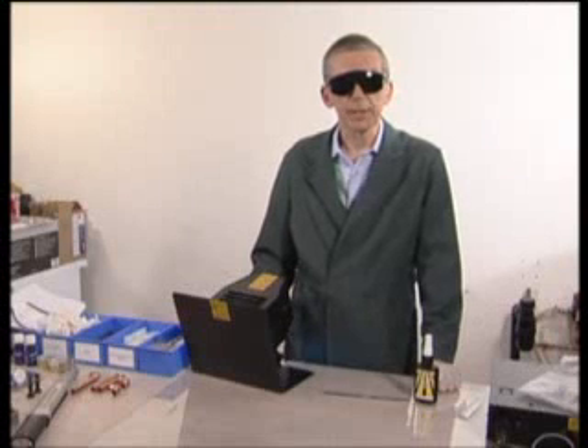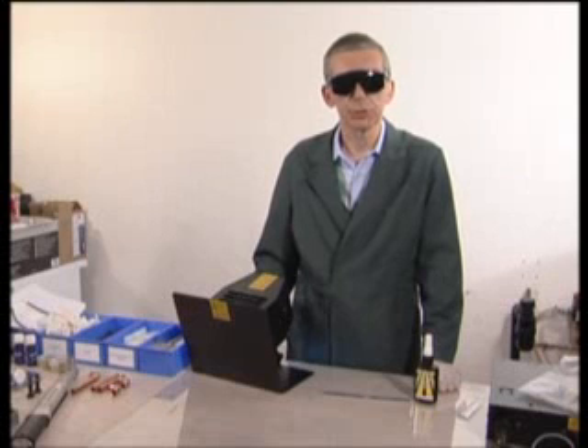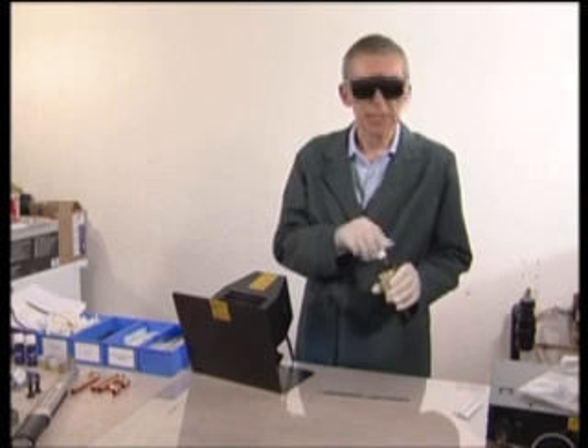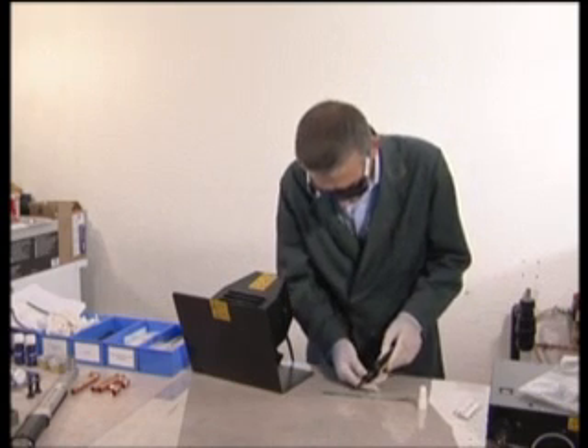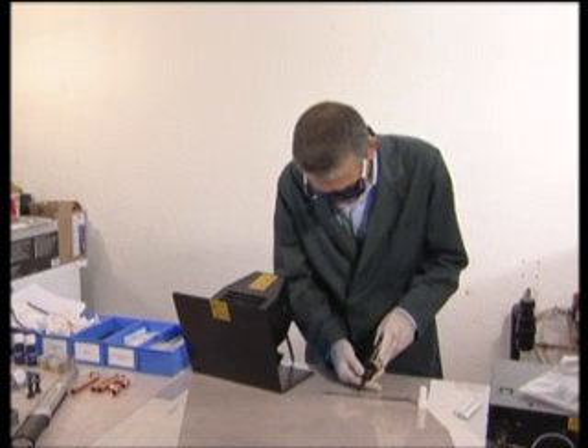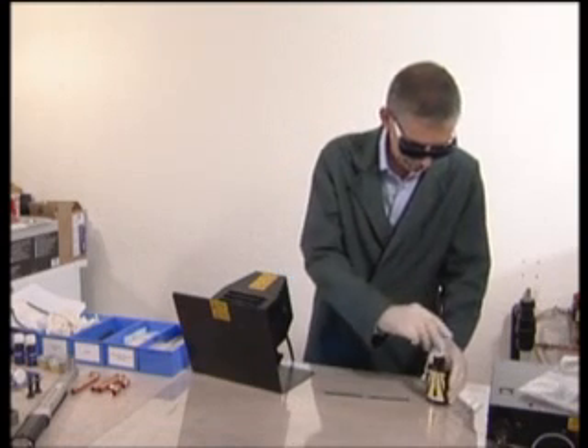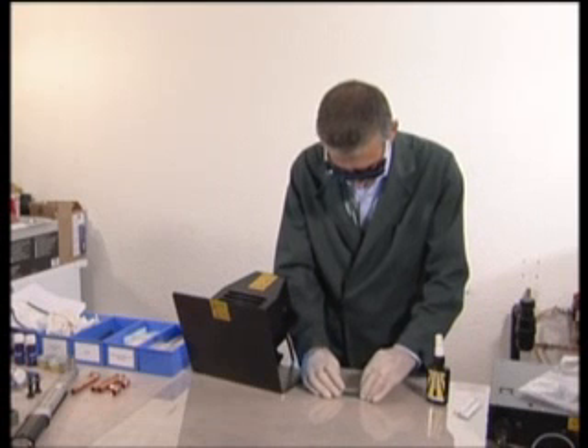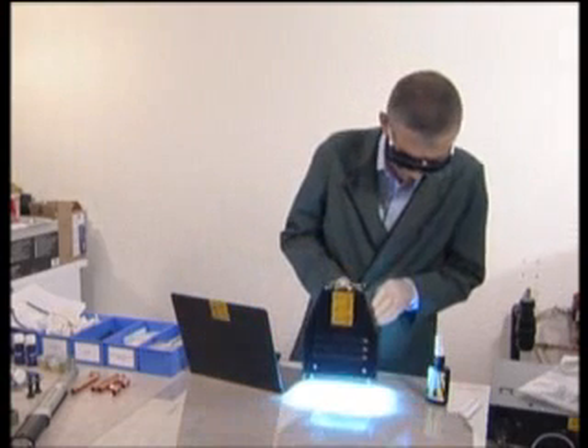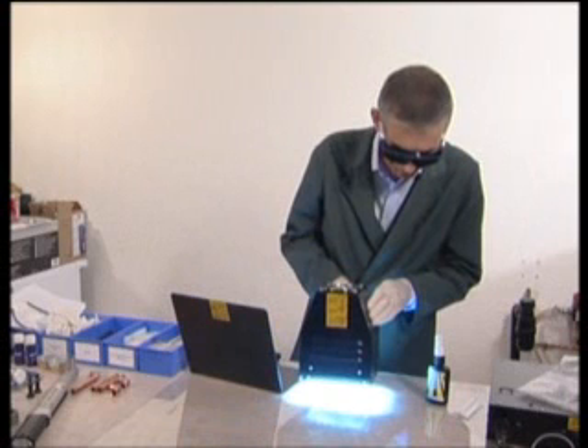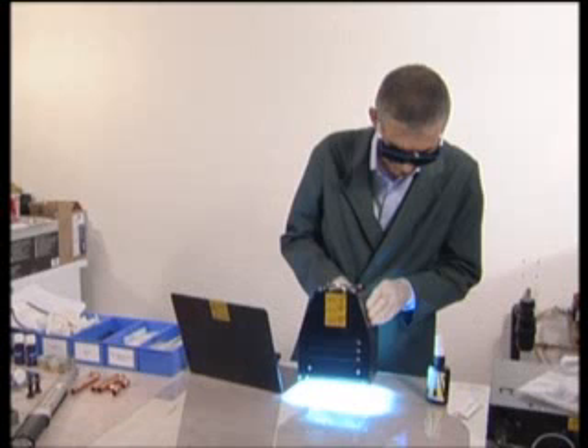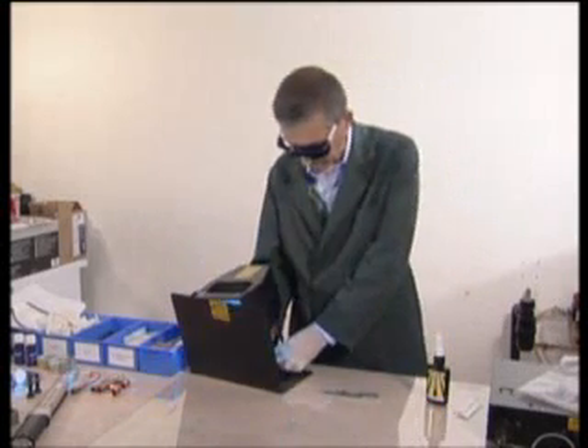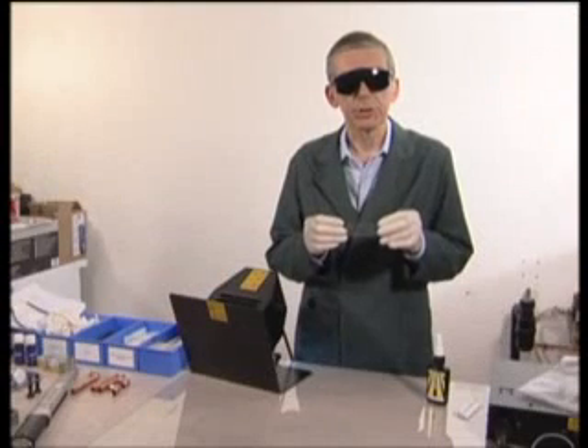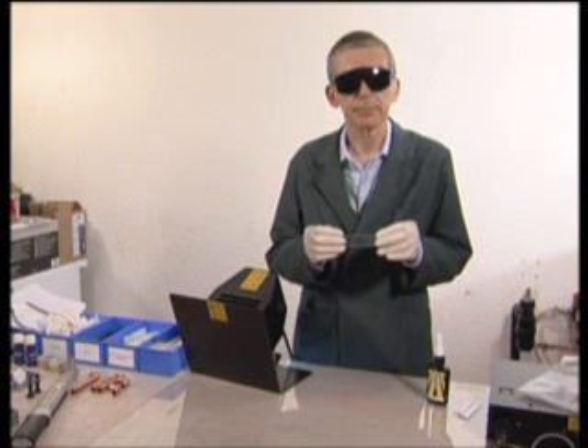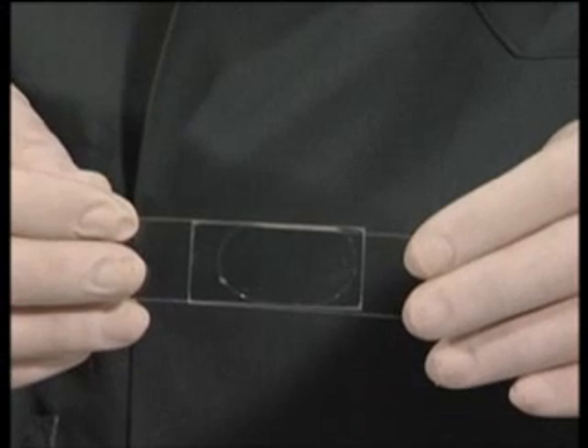Rightlock UV products are used widely for bonding glass and clear plastics to themselves and to other substrates. UV50 is ideal for this application. The product is simply applied and exposed to the UV light for just a few seconds to achieve a very high bond strength. As you can see, the bond line is extremely clear because the UV adhesive has a refractive index very close to the glass. It has high bond strength, impact resistance and environmental resistance.